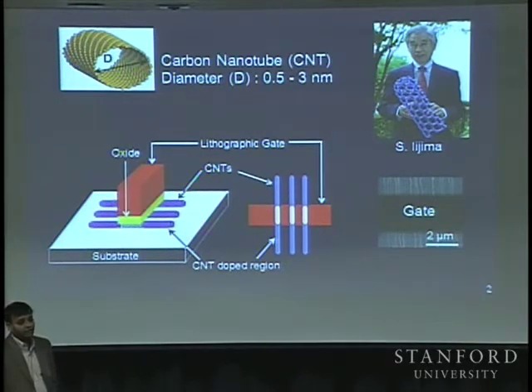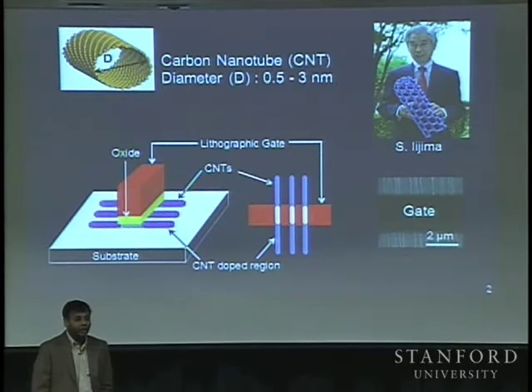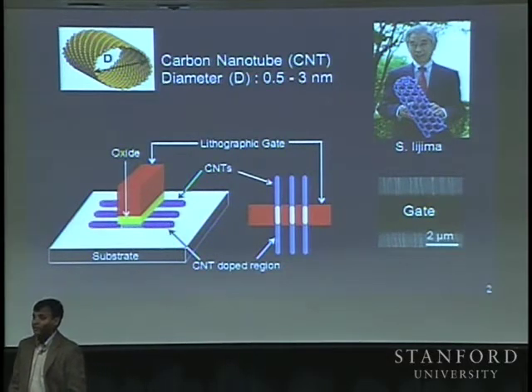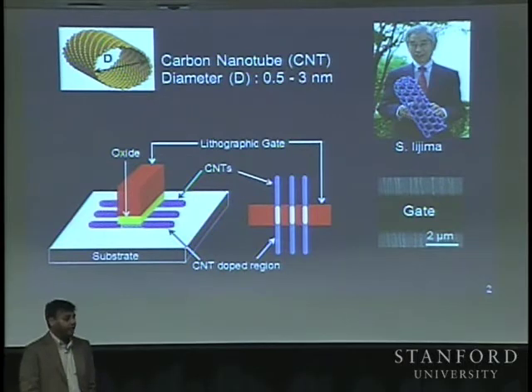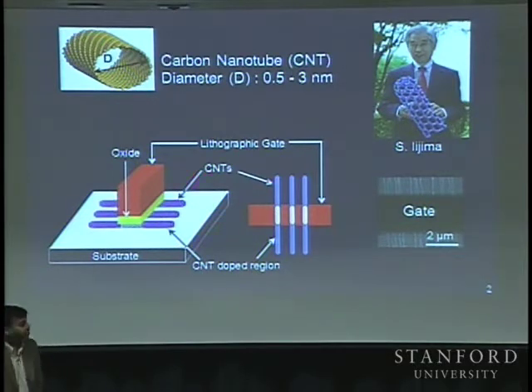So what can you do with these carbon nanotubes? A lot of people talk about making wires out of carbon nanotubes, and there has been some very significant work that has happened in that space. What I will be focusing on is using carbon nanotubes as channel materials in transistors. So here is a cartoon where you can see these carbon nanotubes. So you have grown these carbon nanotubes on a substrate, and I will be going a little bit into how you grow and do all those things. Or you transfer carbon nanotubes from one substrate to another substrate, and then what you do over here is that you build a gate. So for example, this could be something like a hafnium oxide, and then this could be a metal gate.